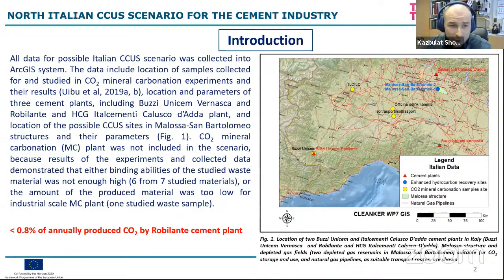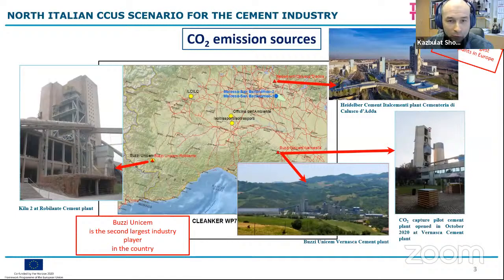CO2 mineral carbonation plants were not included into the scenario because the results of the experiments and collected data demonstrated that the binding ability of the studied waste material wasn't enough. It was less than 1% of annual produced CO2 by Robilante cement plant. So that's why it was avoided.